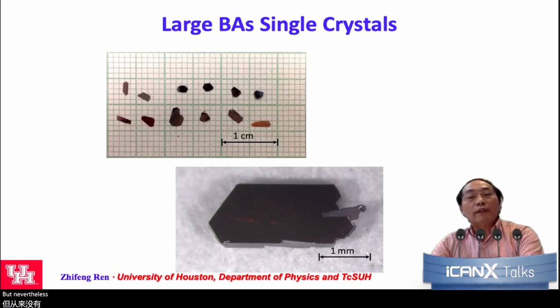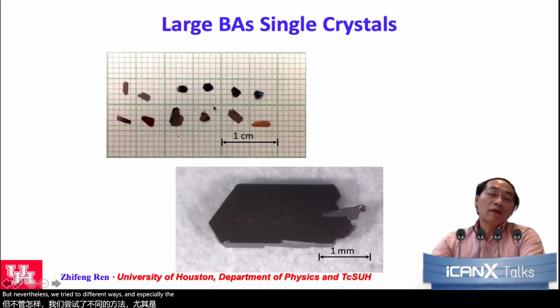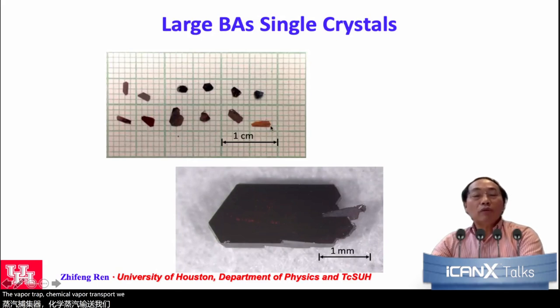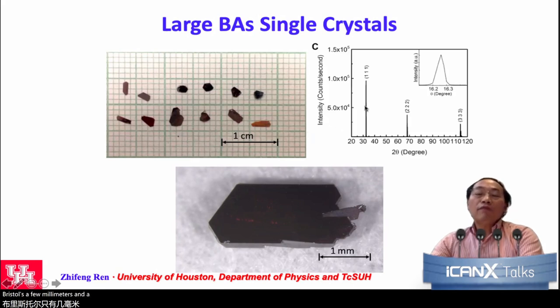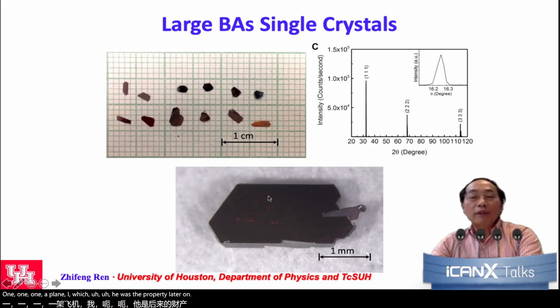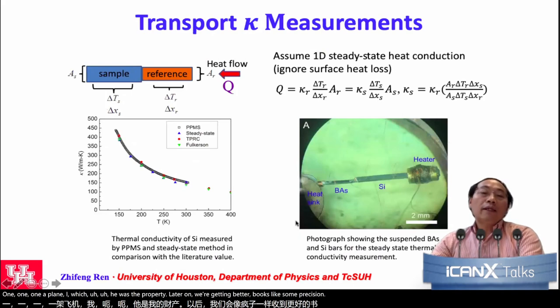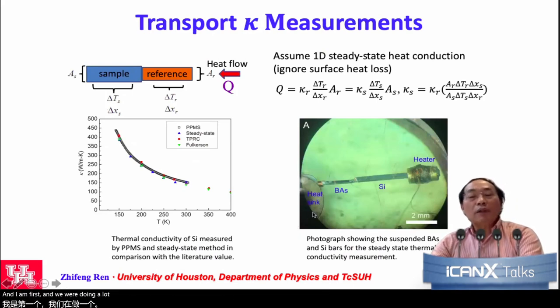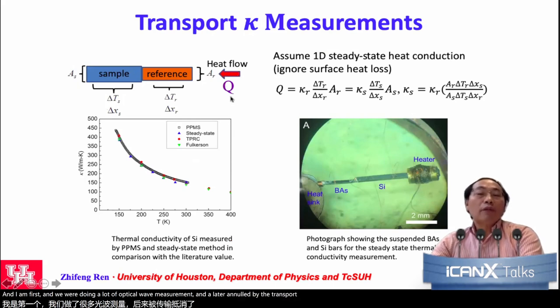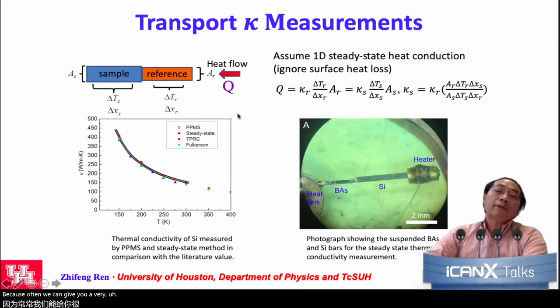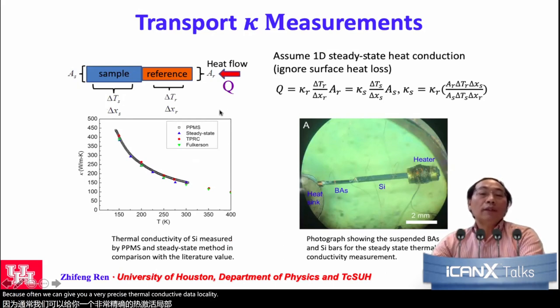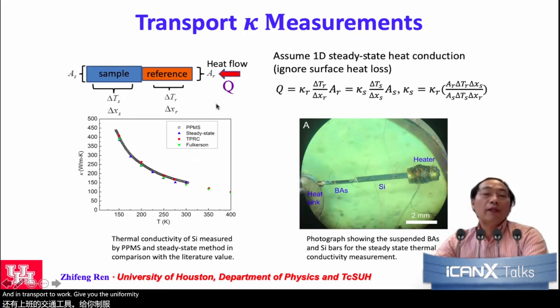Nevertheless, we tried different ways, and especially with chemical vapor transport we were able to grow crystals a few millimeters in size, and found they are indeed single crystals. Most of the planes are 111 planes, which give us the property. Later on, we did the measurement. Some crystals look like this. First we did a lot of optical measurements, and later on we tried transport, because optical measurement can give you very precise thermal conductivity in a local region, and the transport measurement will give you the uniformity of the property.